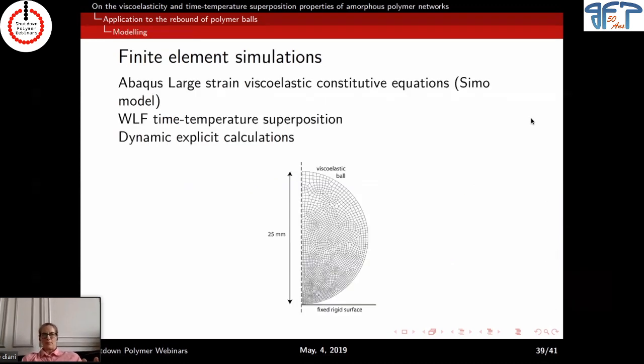And so once again, we characterize by linear viscoelasticity. Well, actually, this one is the same material, the same acrylate. So we have the linear viscoelastic behavior, the time temperature superposition. So the same constitutive equation, and we run dynamic explicit finite element calculation with Abaqus again, and look at the bounce.